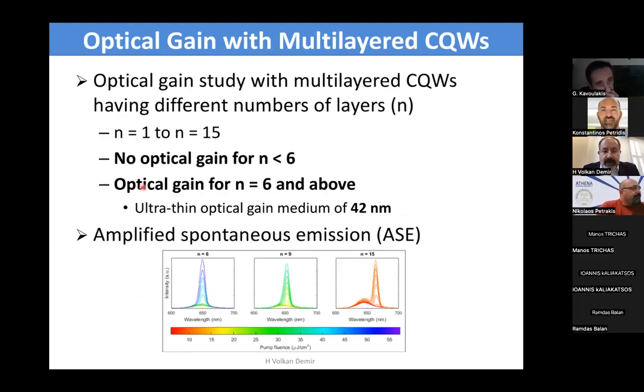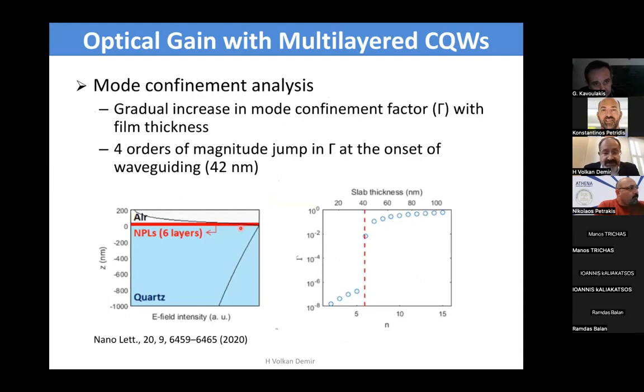With this technique, we observed that only with 6 monolayers and beyond, we can have gain. Directly on quartz, for thinner layers, there is no way to observe gain. To understand the reason, we looked at it numerically, and what we found is, as expected, with quartz and so thin a gain medium and no special optical design, we have a very strong optical leakage into the substrate. As a result, the overlap integral of the supported mode with the gain is very low. Indeed, going from the first monolayer to the fifth monolayer, it is practically zero, very low, in the range of 10 to the power minus 8 to 10 to the power minus 7. And then with the sixth monolayer, there is a sudden jump, explaining the reason why experimentally we observe an onset of gain. And going beyond, as expected, we get only better gain performance.